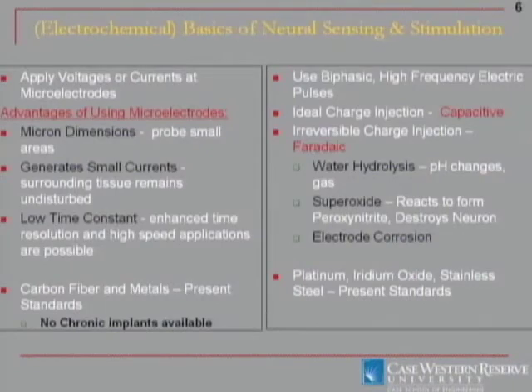In terms of the electrochemical standpoint, both neural sensing and neural stimulation, and I say neural sensing in terms of neurochemical sensing here, they do have an electrochemical basis. For neural sensing on the left here, you are applying either a voltage or a current to an electrode. It's a microelectrode on the order of 10 microns or so. We do, of course, like the size because of the spatial resolution you can get, but the currents are small, which should then reduce the idea of tissue damage from high amounts of current. And the size of the electrode also changes the mass transfer to the electrode, which allows you to use it at a faster time resolution, so you can get down to that millisecond time resolution to monitor things in real time as the neuron is activated.